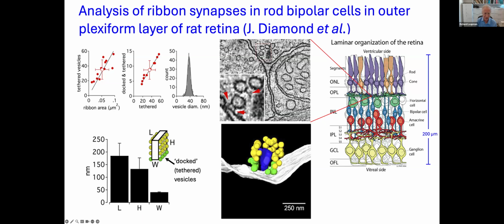So that was an interesting project where I think it demonstrates that you need... I mean, this was done with STEM tomography, but it nevertheless was a thick volume compared with what one would normally do in electron tomography, where one would only be looking at a sample maybe 200 or 300 nanometers thick, and where you would miss certain features of this structure.